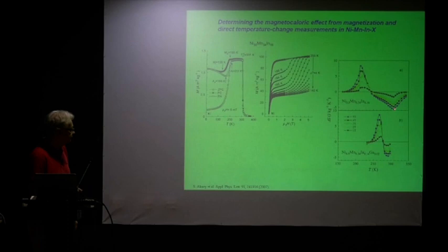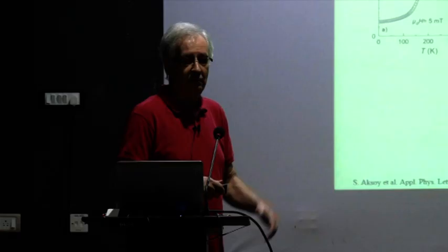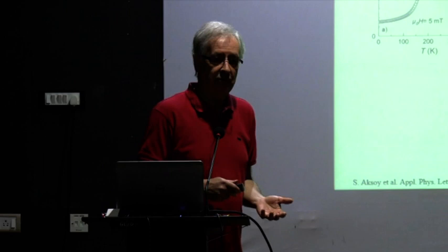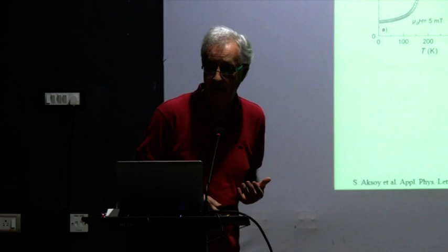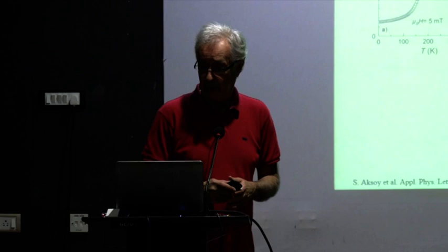It's quite interesting here that you have an entropy change in this direction of a certain value, and in the other direction, well, that's also not too bad. So in both directions, in this particular material, you can observe the inverse magnetocaloric effect as well as the conventional magnetocaloric effect. It can show you both, depending on which temperature range you are.